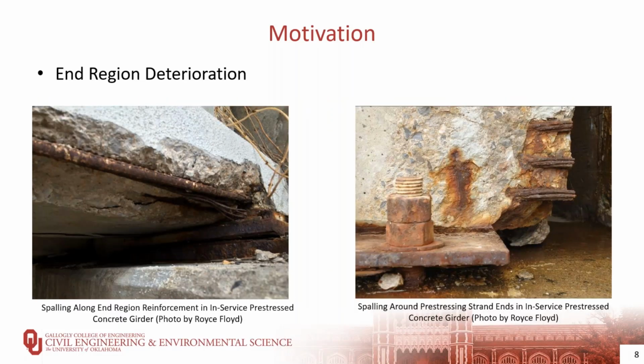Well, the problem that we saw in Oklahoma specifically is that water leaking through the joints onto the ends of the pre-stressed concrete beams can lead to corrosion of the reinforcement, spalling of the concrete in the end region, which can impact the shear behavior and also the transfer of the pre-stress in the end region. Oklahoma has sponsored several projects on behavior of older bridge girders in their pre-stressed bridges, as well as methods for repair and rehabilitation of these end regions. And in light of the previously mentioned design concerns and exposure of these end regions, alternative methods for design and construction have a lot of potential to improve pre-stressed concrete beam performance.